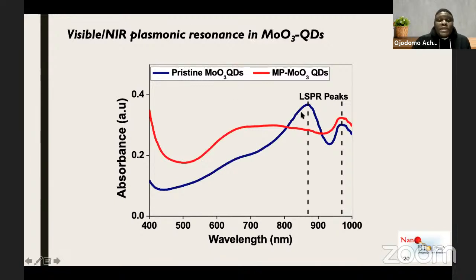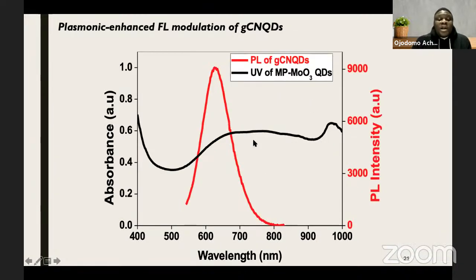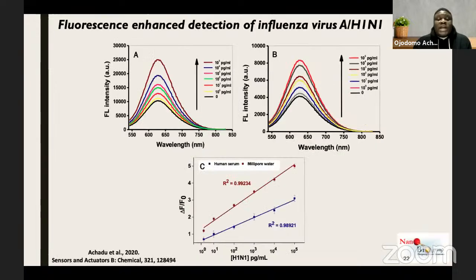So using the molybdenum trioxide, using their plasmonic coupling with the excitation spectra or the emission spectrum of the graphitic carbon nitride, we can see that we experience some kind of plasmonic enhancement in the emission of the graphitic carbon nitride. This kind of interaction can also lead to a concentration-dependent increase in the signal, because in the presence of different amounts of the virus, we can bring two or more of the molybdenum material closer to the surface of the graphitic carbon nitride quantum dots, so that this will experience some kind of enhancement based on the plasmonic resonance and coupling interaction.